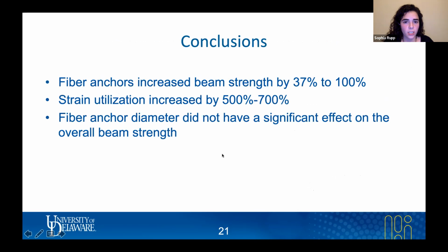So I just touched on this, but I would like to still summarize the main findings that we found so far from my SLC beams that were tested in preliminary testing. As I mentioned, we found that the fiber anchors increased the beam strength from about 37% to 100%. The strain utilization increased from about 500% to 700% between the anchored and unanchored beams. And then finally, what was really interesting to see was that the fiber anchor diameter size really did not have any significant effect on the overall beam strength.